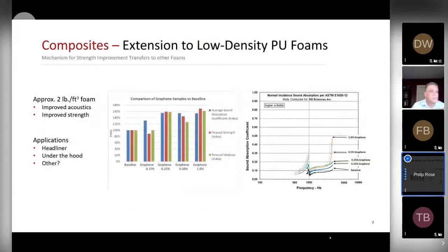Of course, we're also able to extend the performance benefits to other polyurethane foam systems. This slide provides performance data for use in lower density polyurethane foams. The bar chart on the left summarizes the change in flexural strength and modulus, as well as average sound absorption coefficient for samples without graphene nanoplatelets and those incorporating graphene nanoplatelets from 0.15 to 1% by weight. And as you can see, even small amounts of graphene nanoplatelets will improve the performance, and as shown here, from 50 to 60%.